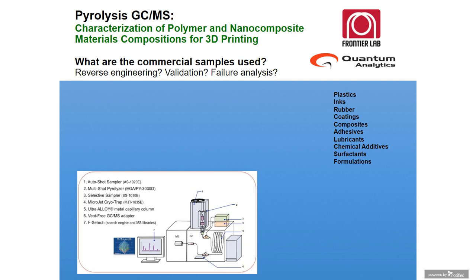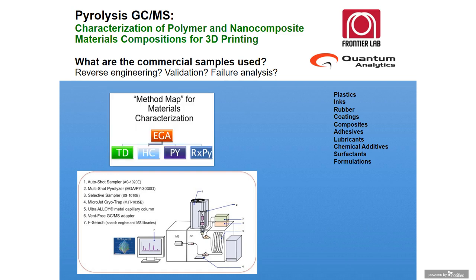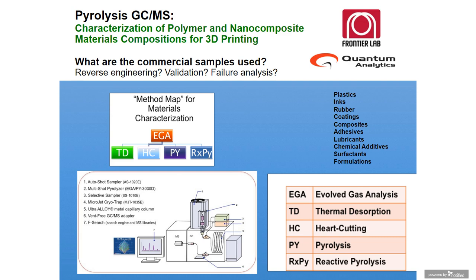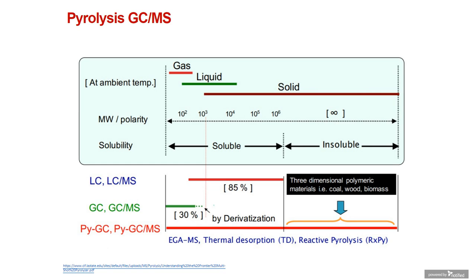We have been using this actually for characterizing cross-linking density as well as molecular weight determination in conjunction with other techniques. So you've heard techniques like thermal desorption, evolved gas analysis, heart-cutting, etc. And these are the abbreviations that are shown in this method map. And the more you use them, the more you find, of course, the specific advantages of each one. The nice thing with this GC mass spec pyrolysis method is that it encompasses the three phases of your sample from gas to liquid to solid. Whereas if you simply use LC or LCMS or GC, GCMS, you're dealing only with specific phases or mobile phases during the analysis.